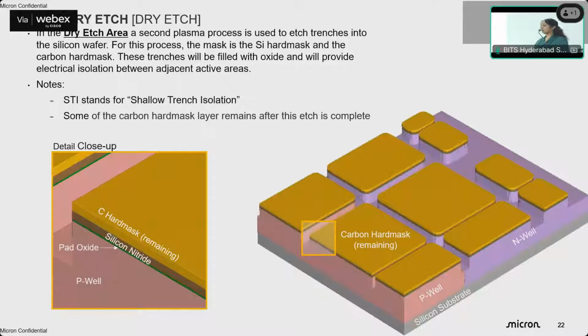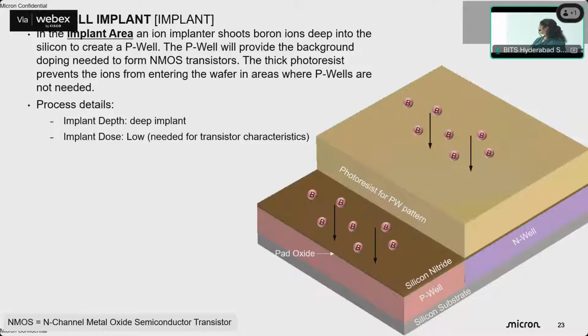So here is an example of a dry etch trench, where it has gone through the carbon hard mask, the nitride, the oxide, and a little bit into the silicon as designed. And here is a 3D view of implanting using photoresist. As you can see, certain areas are masked completely, whereas the area where you want to change the material property is open.